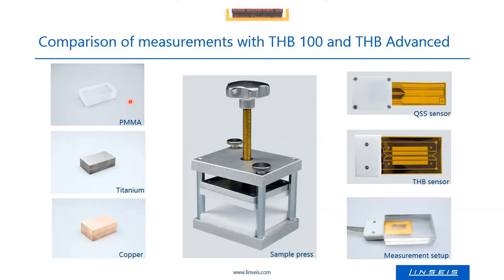And for the PMMA, we used for both instruments the THB sensor, and for the higher conductors, for the metals, we used a QSS sensor. We took two sample halves, put the sensor between the two sample halves, and pressed it with a press. You need around 0.5 bar contact pressure, which is around, for this sensor size, equivalent to around 3 or 4 kilogram of load on that setup.